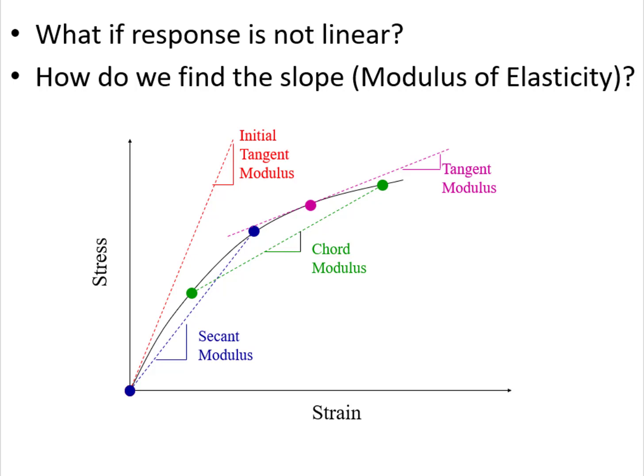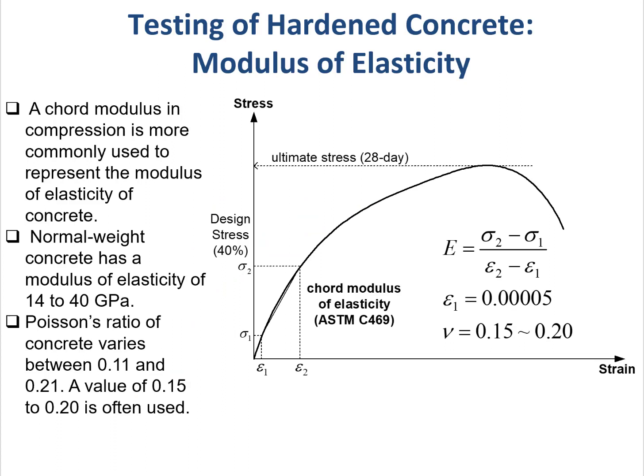The initial tangent modulus is the slope of the tangent drawn at the origin of the stress strain curve, and the tangent modulus is the slope of the tangent drawn at an arbitrary point on the stress strain curve. The secant modulus is the slope of the chord connecting the origin and an arbitrary point on the stress strain curve, and the chord modulus is the slope of the chord connecting 2 points on the stress strain curve. To calculate the modulus of elasticity of concrete, we often use the chord modulus.